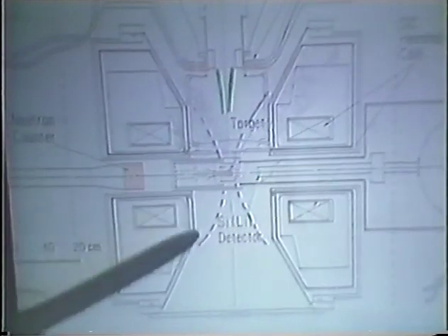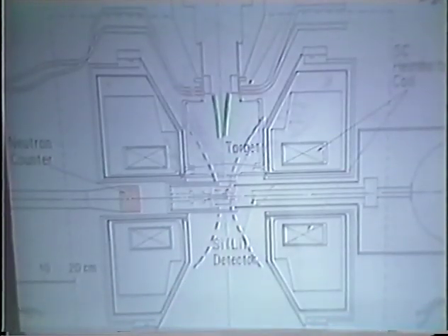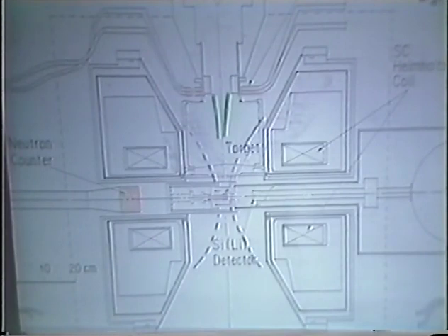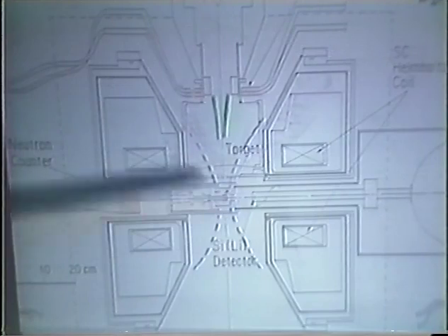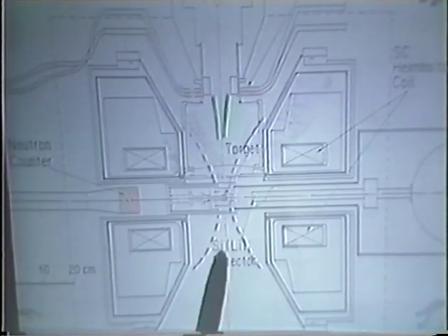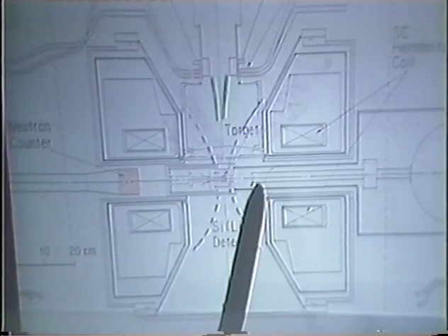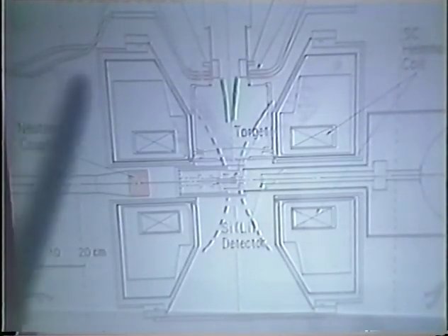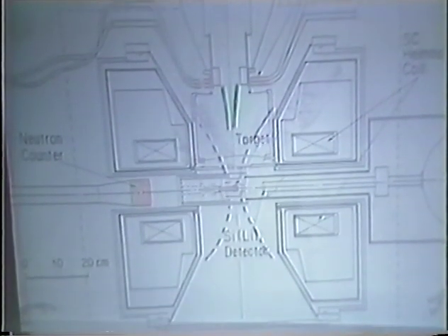It has a superconducting coil winding like this, and because of this high longitudinal field, first of all, the muon is focused into the small target, and also all the mu decay background, which may hit either the Si(Li) X-ray detector or the neutron detector, stays away from these counters. And here we install mu decay counters in order to measure the atomic capture ratio.